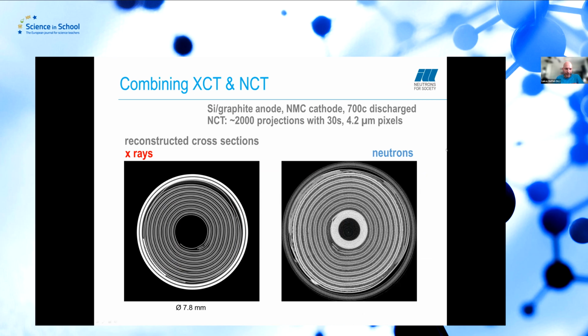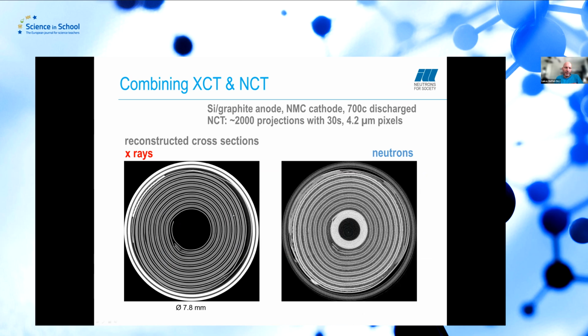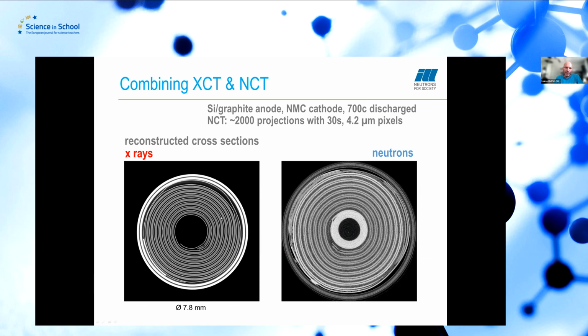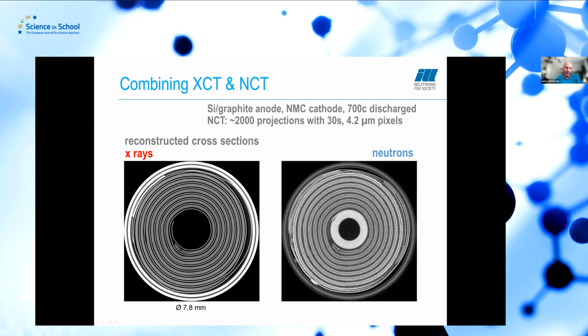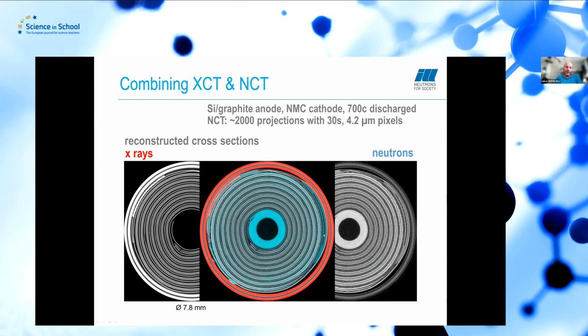For that, as already shown by Alessandro, we can use both X-rays and neutrons in order to very well characterize the different components of the battery. So here the X-ray image doesn't need to be done with the same pixel size or spatial sampling. So here we just increase the pixel size and turn the image in order to make it approximately match here. And then we can create a composite image where you show the highly absorbing X-ray in red and the highly absorbing neutron in blue.